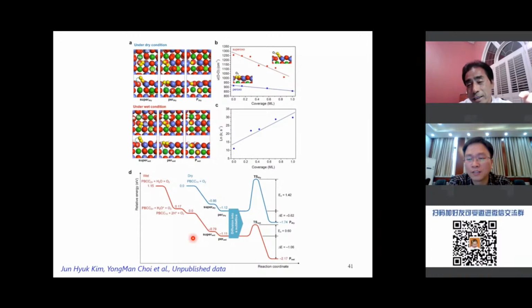However, vacancy is not the only thing. If vacancy were the only thing, there are more efficient ways to introduce more vacancies. But vacancy is important. Definitely, vacancy plays an important role. But in addition to vacancy, you also need nickel cation and ruthenium cation. They do other things, like breaking the carbon-hydrogen bond and breaking the oxygen-hydrogen bond. For those catalytic properties, oxygen vacancy is not efficient. So you need all of them to work together. You're looking for this synergistic effect. But to answer your question, yes, vacancy is important, but vacancy can be easily created in silver oxide. Vacancy is not the only factor. It's an important factor, but not the only factor.